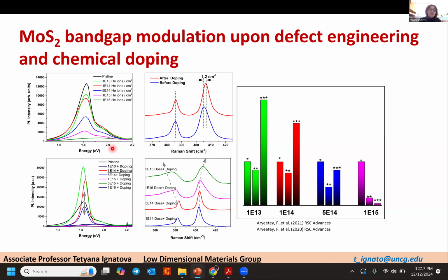The same sample was then defected and doped with p-dopant, and you can see it started with the black curve, the same as here. Then instead of quenching of photoluminescence, we observe enhancement of photoluminescence as well as a shift. After a certain value, it started to be quenched the same way as for the just defected sample. Results of this method are presented on the right panel. You can see that for multiple doses of helium ion irradiation, we have enhancement or quenching of photoluminescence.